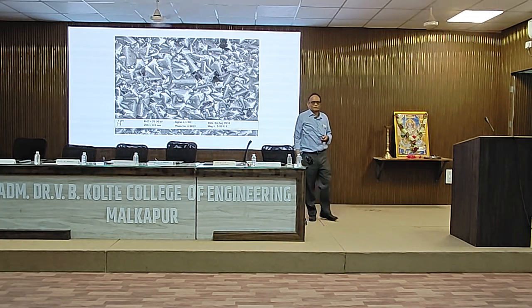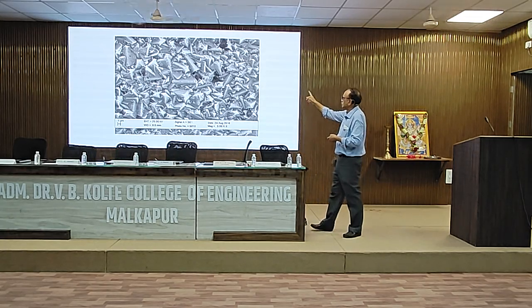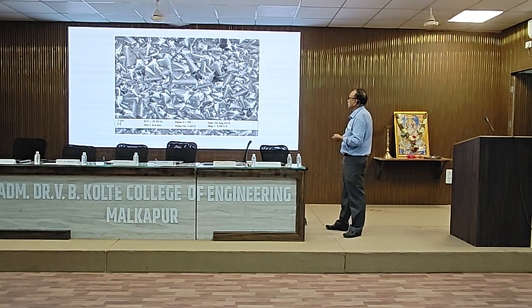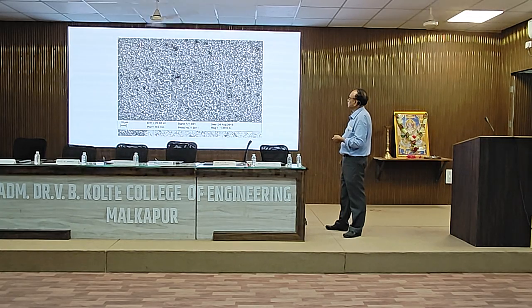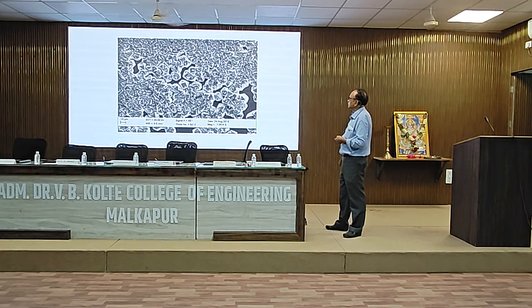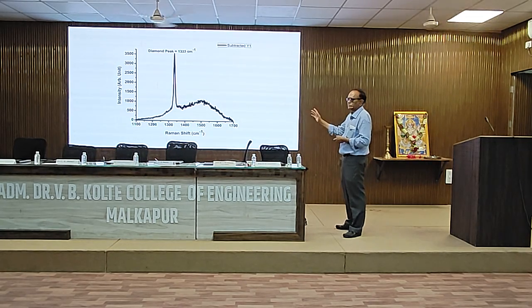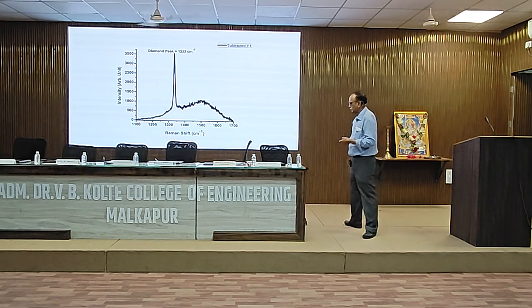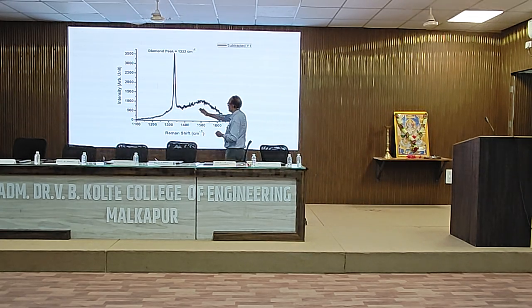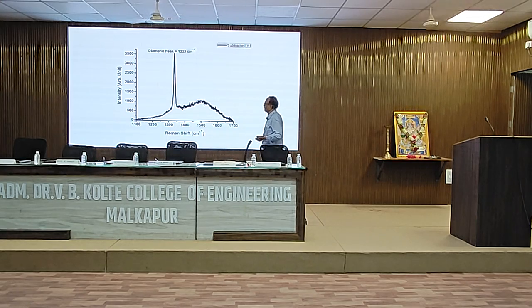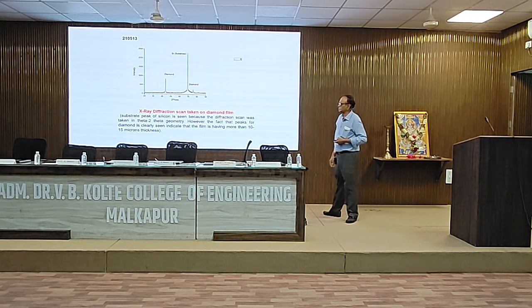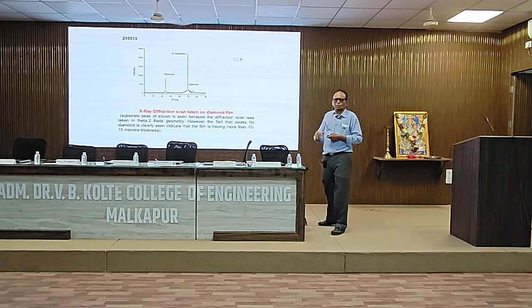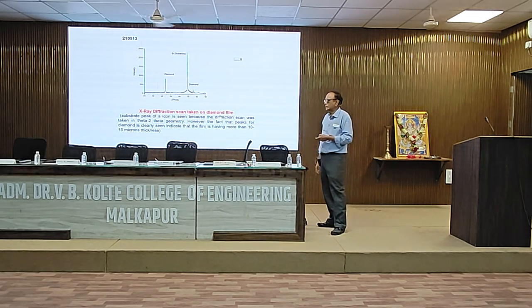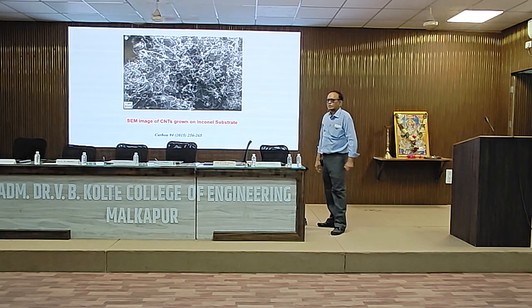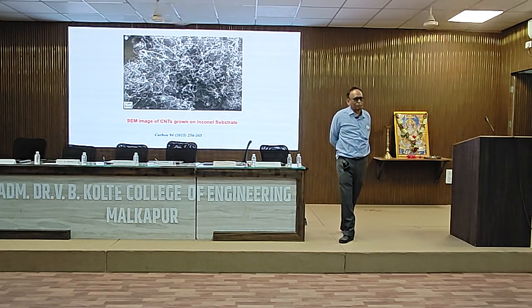And you see, these are the diamonds that are deposited. These are basically the diamond crystals. And okay, these are continuous diamond films. And see, these are the diamonds actually deposited. There are all these characterizations like Raman spectra, typical of the 1332 inverse centimeter Raman peak, etc. That was obtained, and then X-ray diffraction was done to make sure that whatever we have deposited is diamond only and not graphite. So basically, again, this same plasma can be used for carbon nanotube deposition.